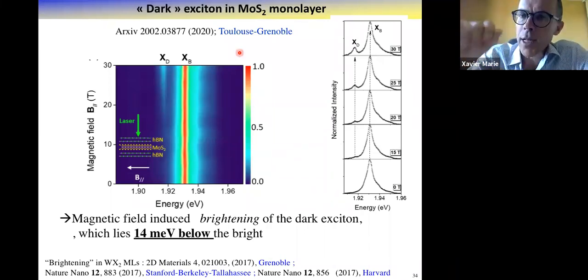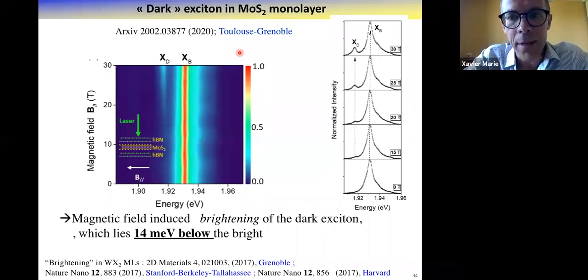We are not calculating the difference between the single bands, but we have an exciton. So the second key ingredient is the exchange interaction. And from the work we did again with Yann Gerber and some measurements we did a few years ago, we estimate that the exchange energy is of the order of 10 millielectron volts. So it pushes the dark exciton 10 millielectron volts below, again due to the exchange interaction between your electron and hole. This is the second ingredient.